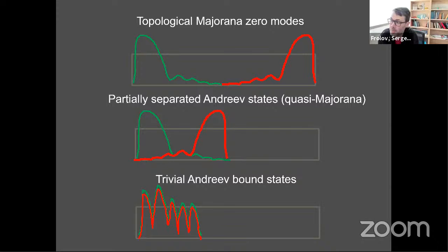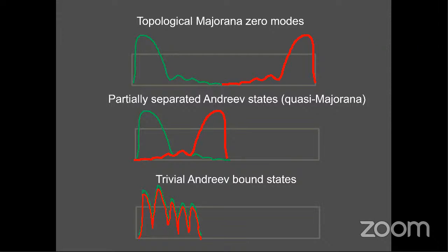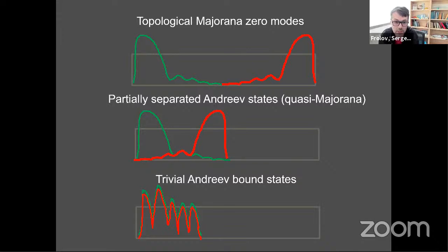But I mean, temperature, what's going to happen is things are going to broaden and die. And so I think at this stage, it is not one of the more useful ones, because temperature just typically confirms what you can see at the lowest temperature. Let's say if your peak width is 20 microvolts, at 100 millikelvin it will disappear. Things like that. But in the future, it can be a useful control knob. For instance, if we establish this topological gap we talked about, we can study to what temperature topological protection extends, and that could also be a measurement of this gap. We can also study, some people propose some thermoelectric signatures. So that could be temperature dependent.